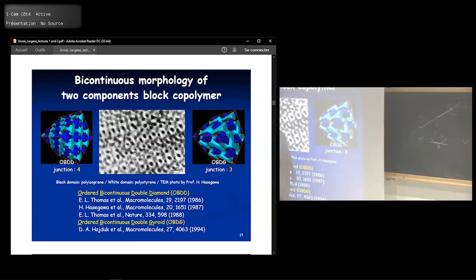And it's a double structure. The blue one and the light blue one are domains with the 34% volume fraction, but these two are not intersecting each other. They are independent. Okay, so they came up with this OBDD structure, and later on, Professor Thomas reported that this structure is not OBDD but OBDG. G stands for gyroid structure, a different type of minimal surface. So for some time, there was a controversy whether this structure is diamond or gyroid. Finally, I think this paper ends the discussion with very precise X-ray scattering analysis. This structure was proven to be the gyroid structure.